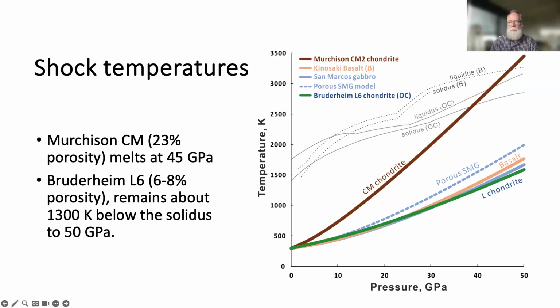But if you look at the other samples, Bruderheim L6 and the basalt and the gabbro, they remain about 1300 degrees below the liquidus, up to 50 GPa. And so the shock does not melt the whole sample until you get to very high pressures. At higher pressures, this will go up and intersect the melting curve. But what it's telling you is that in this range of pressures that we're interested in, the temperature of the bulk rock is much colder than the local melting. The local melting results from these local excursions, collapse of pores, collapse of fractures, and frictional melting. And so we have local hotspots in a matrix of relatively cool material.